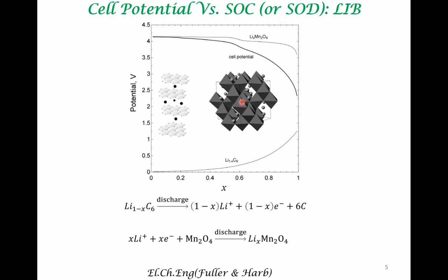Okay, so the thermodynamics of the lithium ion battery with LMO cathode and graphite anode is dependent upon two kinds of lithium ion interaction. The one interaction is when lithium is in the anode. During discharge, lithium that is intercalated in the anode host, the graphite host, gets out into the electrolyte and gives out an electron which goes through the wire.